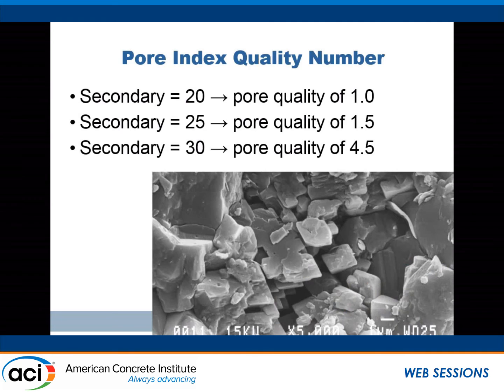But again, what it's doing is using how easy it is to push the water into the concrete to get a handle on that pore size distribution. And again, they've come up with these quality numbers based on the different numbers that are coming out of the test. So again, we're qualifying it as to what is good, bad, and not so good.